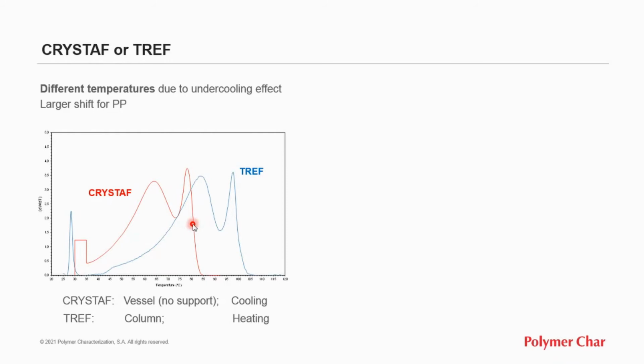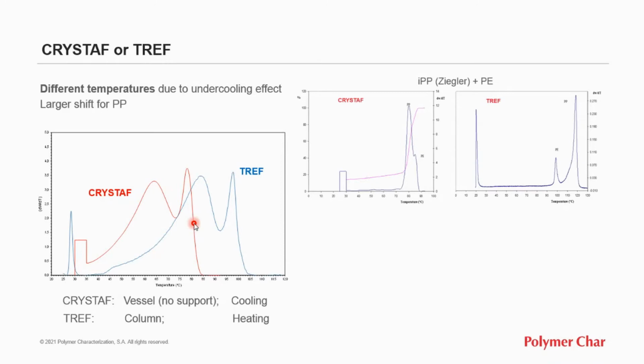So there is a shift to higher temperatures in TREF, as we can see here. That shift is larger for polypropylene than for polyethylene. For that reason, some polymer combinations are not resolved by Crystaf, as we can see here, but they are separated by TREF. That's the case of isotactic polypropylene and homopolymer polyethylene. That can be resolved by TREF, and Crystaf would coelute.